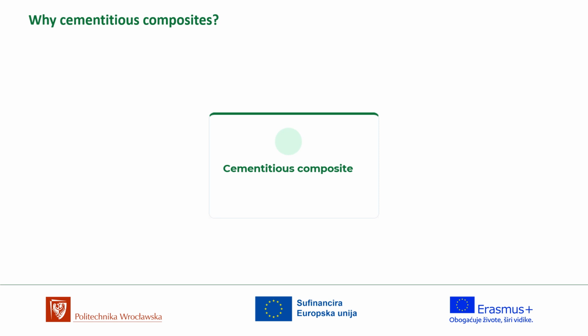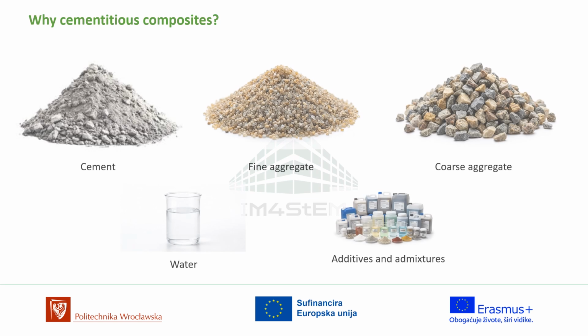Starting with cementitious composites. Cementitious composites basically consist of, first, Portland cement, which acts as the main hydraulic binder. Second, different types of aggregates, fine and coarse aggregate. Third, water, which triggers the hydration process. And fourth, chemical admixtures or various other additives, such as superplasticizers to control, for example, workability and the water-to-cement ratio, or other fillers to make the cementitious mixtures denser. Together, all of these ingredients create a concrete matrix that can use, for example, recycled materials in other ways, like for example fly ash or any other.